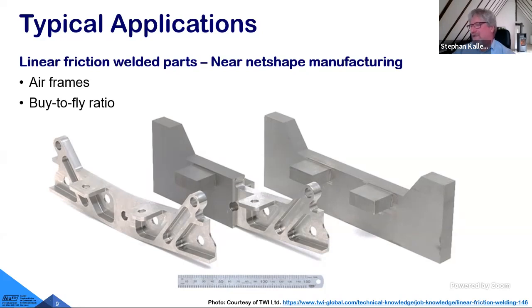the weld integrity is so high that it is nearly not possible to distinguish it from the parent material. So we have a very refined microstructure and very high strength. So in titanium there is no significant decrease of strength in the weld area. The main purpose is to improve our buy to fly ratio.